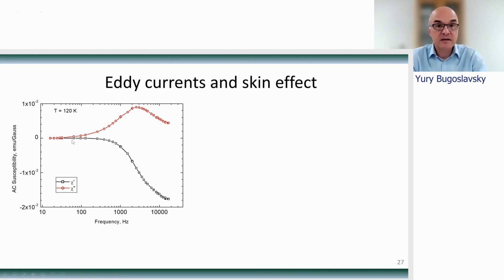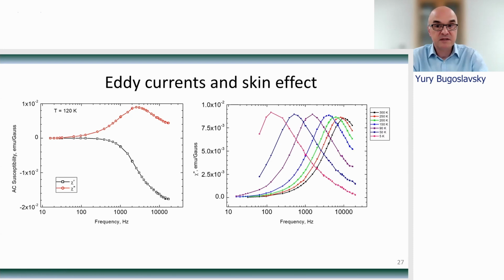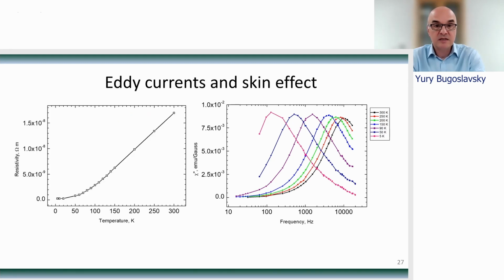And we see here that the peak of the imaginary part now coincides with the point where the skin depth becomes equal to the radius of the sample. Now, using the formula, we can map the frequency of this peak to the conductivity. Repeating the same experiment at different temperatures gives us this nice set of curves. Here, the low temperature data has a peak on the left corresponding to low frequency, and as we increase the temperature, the peak shifts to higher frequency. Processing this data, taking the position of the peaks and converting them into the resistivity, we get this graph, which is a perfect match to what we expect for the resistivity of copper.